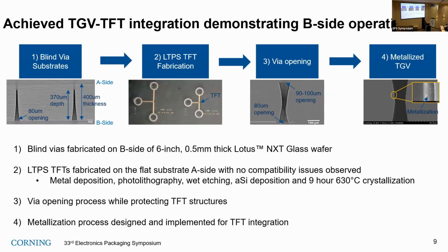Here are the results of each step. Blind vias were created 370 microns deep in a 400 micron thick glass, and then we fabricated TFTs on it. Each gate, source, and drain is connected to the via. It is supposed to be opened after the TFT fabrication. Here we opened the via with an 80 micron opening on the TFT side and a 90 to 100 micron opening on the back side, which is connected to the driver board. That's the conformal metal we did for connecting the A side to the B side. So we don't see big issues, even though this whole stack went through the complex LTPS TFT fabrication process. We don't see any thermal issues or compaction issues with the glass, and we integrated that.